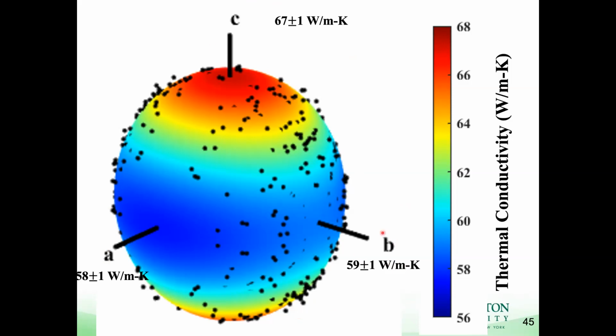So actually, regarding the anisotropy that we saw, I was expecting that we might have much lower conductivity in the B direction, because that orientation has this tenfold superlattice, but we didn't see that.